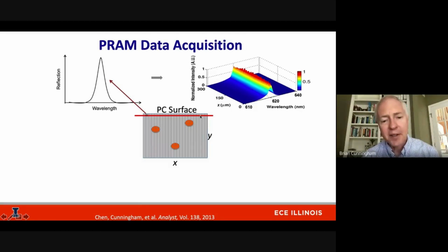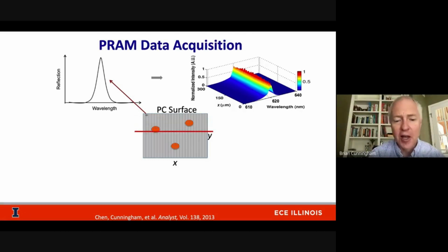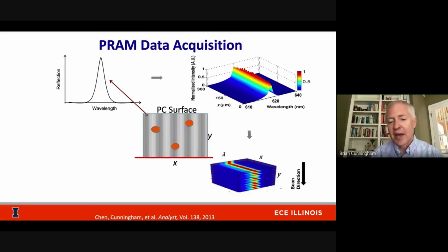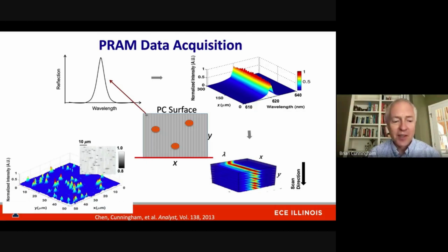And so by moving our photonic crystal under the line in small increments, in about 30 seconds, we can gather a whole stack of reflection spectra from each position on the photonic crystal surface, and then analyze them for their peak intensity value. And so what's shown here is a PRAM image where each dark spot represents the position of one gold nanourchin, where even though they're small, they have very high contrast.